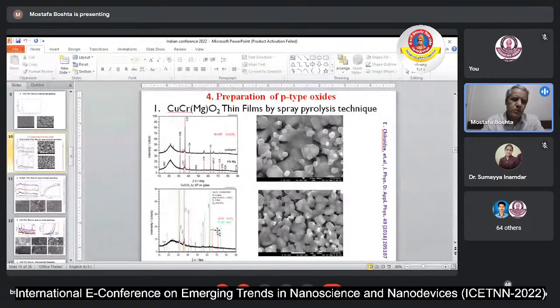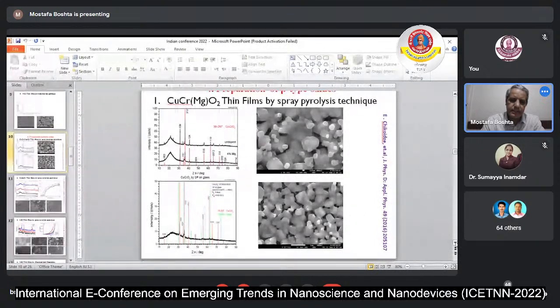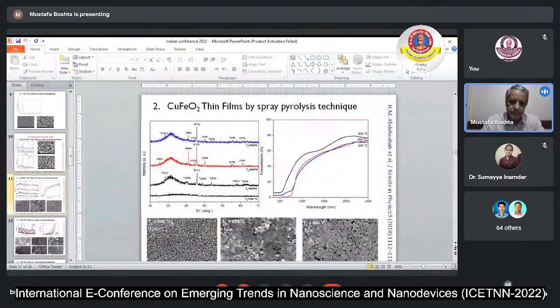Also, we tried annealing this material at a lower temperature, about 600 degrees, but we increased the annealing time. It takes about 1 day or 4 days to anneal this material at 600 degrees to get this crystallinity. And if you look at the structure in the scanning electron microscope, you can find that the grain size is increased and the crystallinity is better with long time and low temperature. That is the quality of the material by spray pyrolysis and the annealing process. It is good for application in some ways.